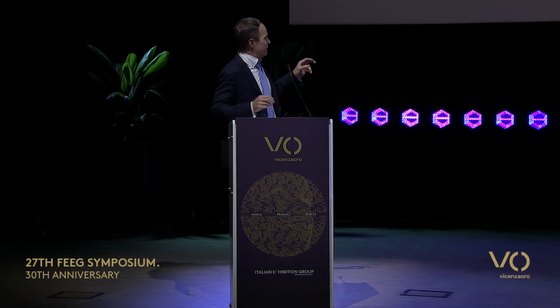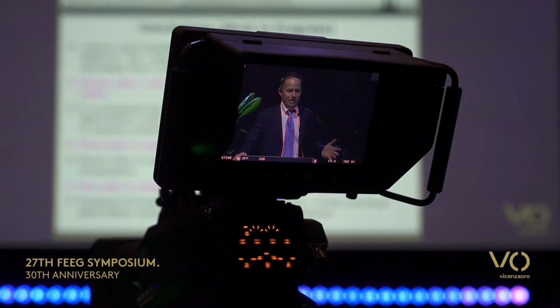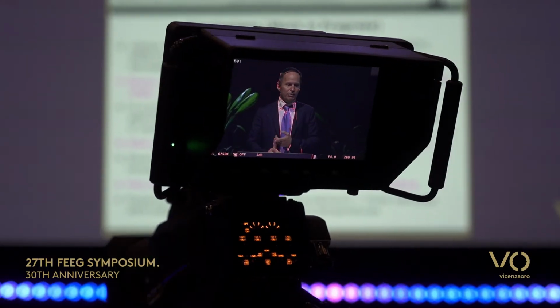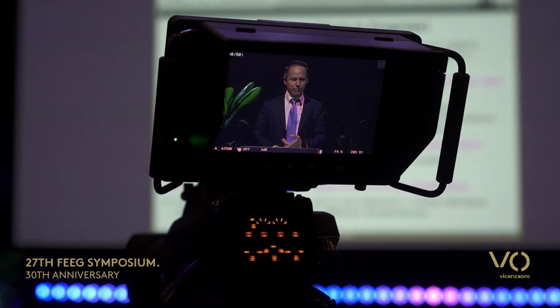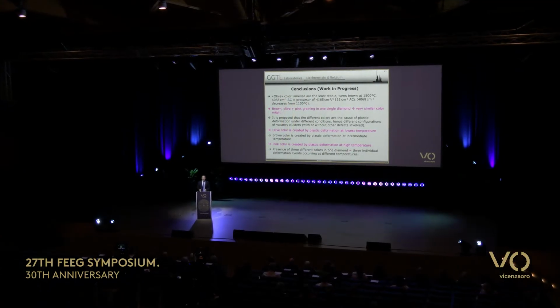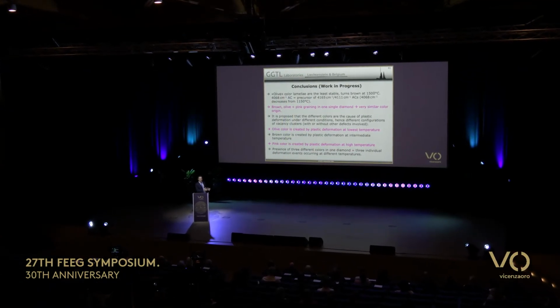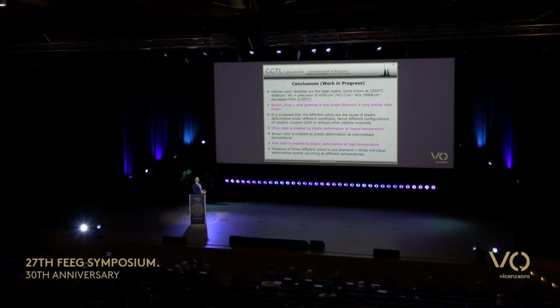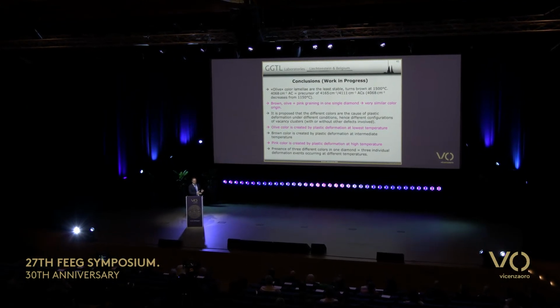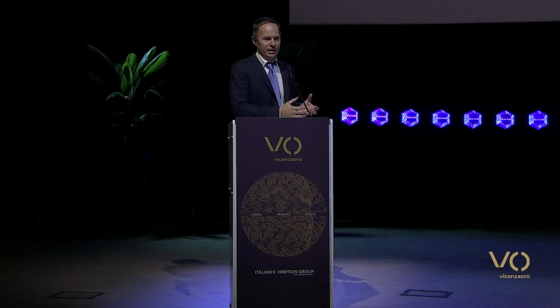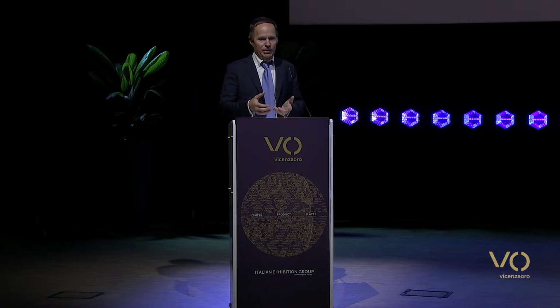So the presence of three different colors in one diamond is quite easily explained. You have three different individual deformation events occurring at different temperatures. Your stone forms, is plastically deformed, moves, or the temperature locally changes, it's plastically deformed again, and moves or the temperature changes and it's plastically deformed again. And there you go, you have three different colors in your sample.